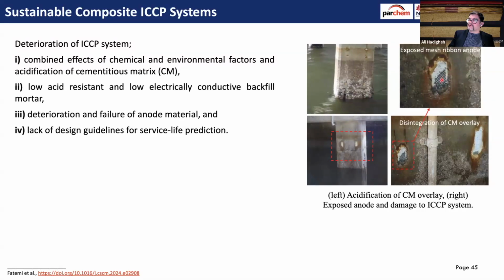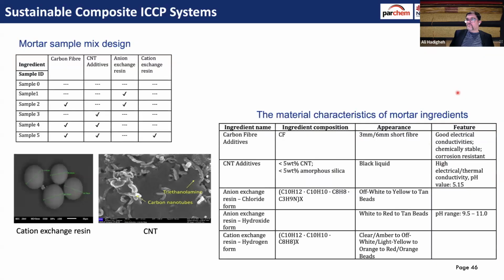You can see this is a mesh anode under the mortar, but after a while this is acidified, and then that washed away and the whole system failed. So they spent millions of dollars on one bridge, for example, to install these, but after a couple of years they washed away, they failed. So they asked us how we can improve these. One aspect was improving acid resistance of these materials, these mortars. We looked at geopolymer concrete, and we are still working on that and improving that.